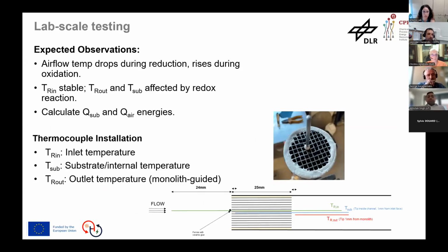During redox cycling, we observe that the airflow temperature drops during reduction and rises again during oxidation. While the inlet temperature remains stable, the substrate and outlet temperatures fluctuate due to the chemical reactions. These variations help us compute the energy exchange with the substrate and the energy delivered to the airflow. This data is essential to quantify the effective energy storage and release during cycling.